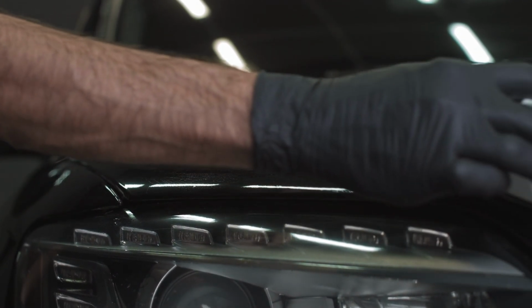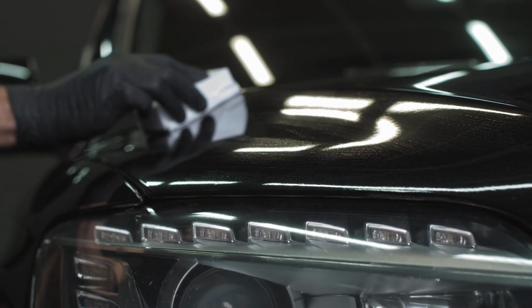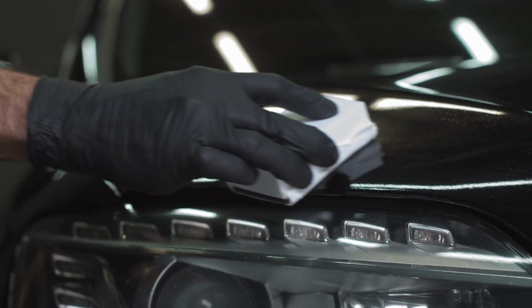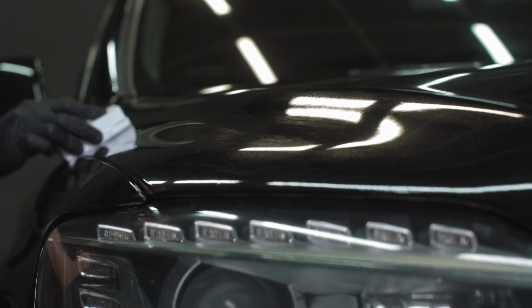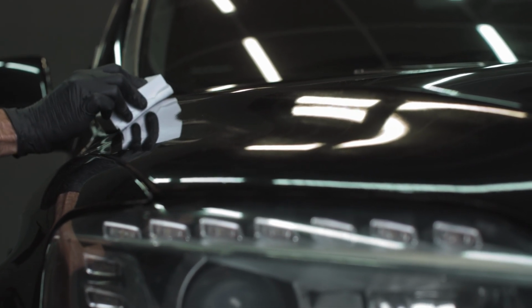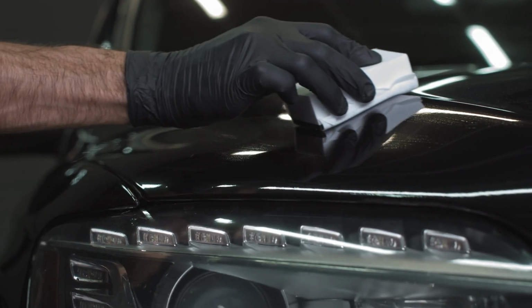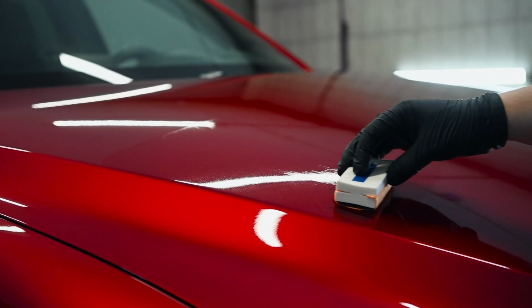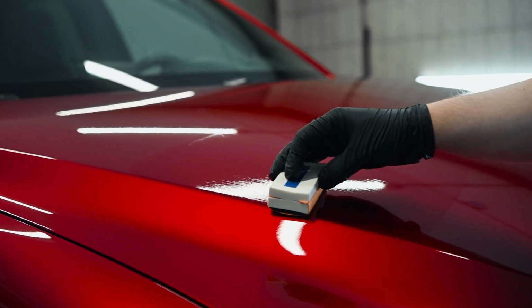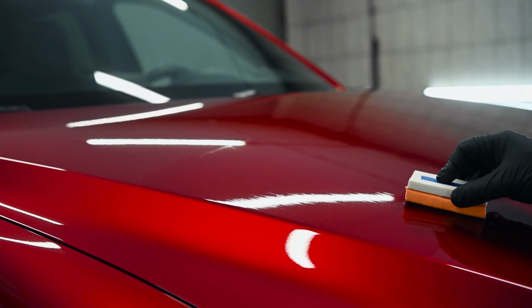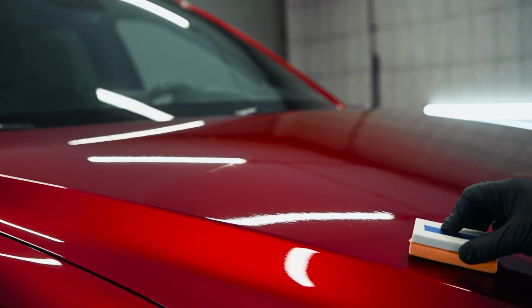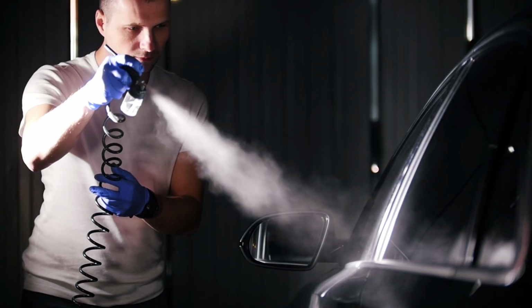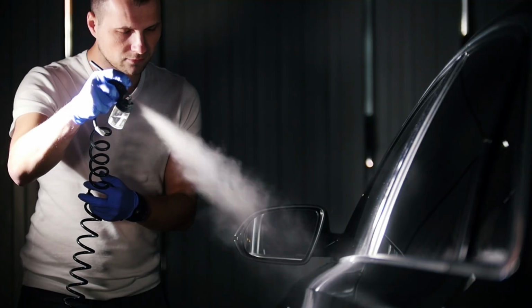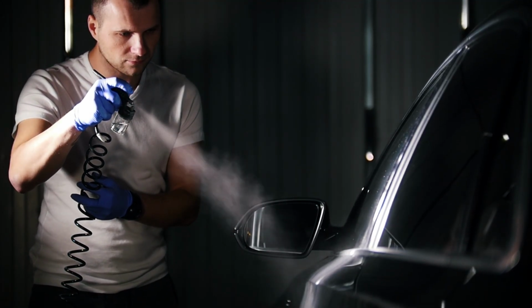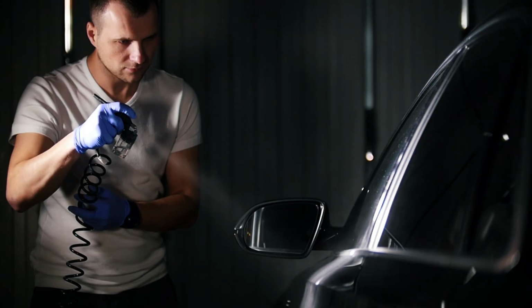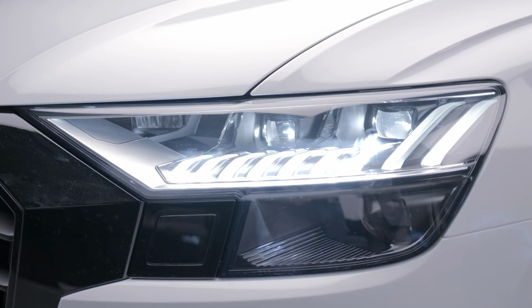The hardness 9H, based on the pencil scale, provides a superior resistance against the micro scratches caused by the washing and the sand of the road. But its greatest benefit is its extreme UV filter and its hydrophobic properties. The water and the dirt simply cannot grab onto the headlight. They slip off before leaving lime spots or mineral deposits. To apply it with success after the polymerization, the headlight must be at a controlled temperature and free of any trace of grease. It is the molecular shield that prevents the sun from yellowing the plastic again, maintaining the transparency for years under the most severe climatic conditions.